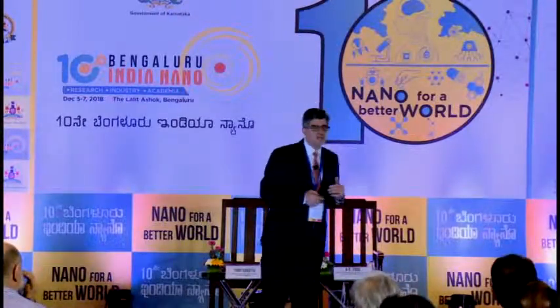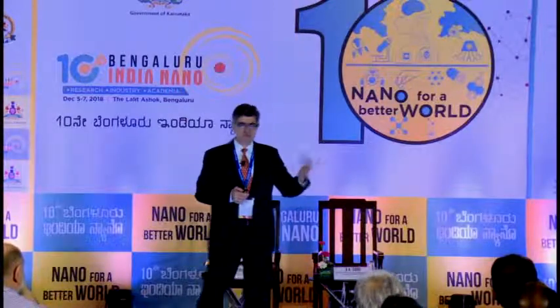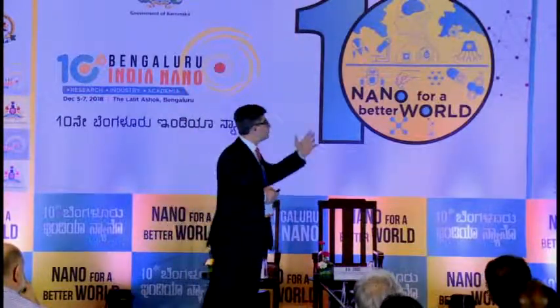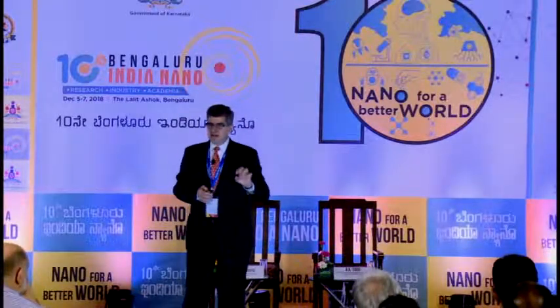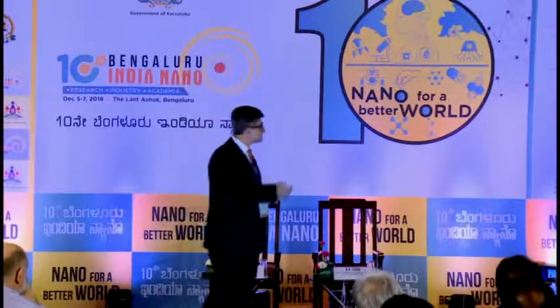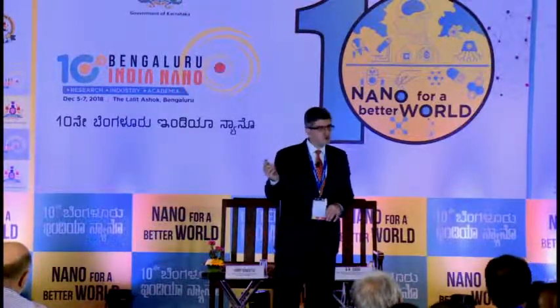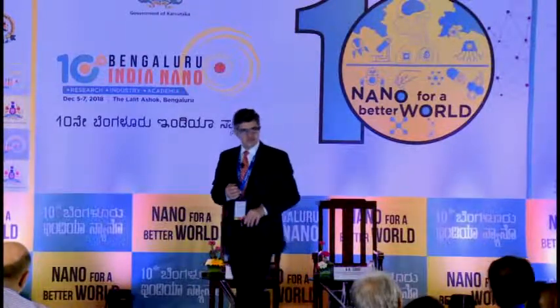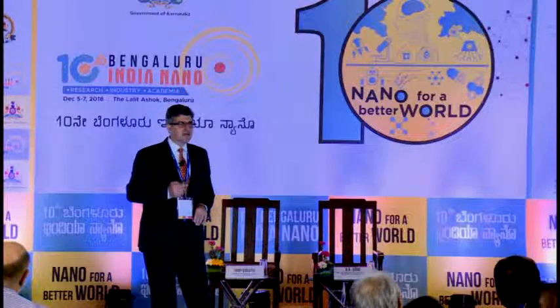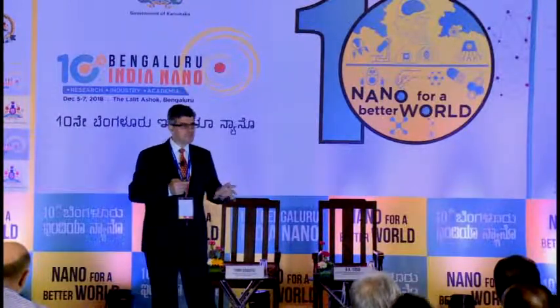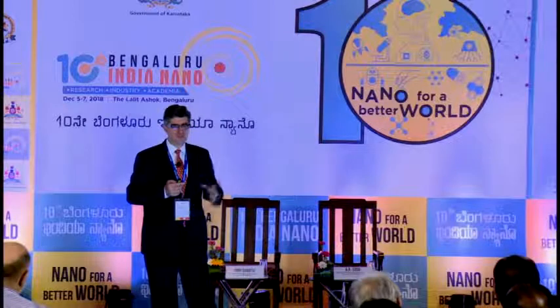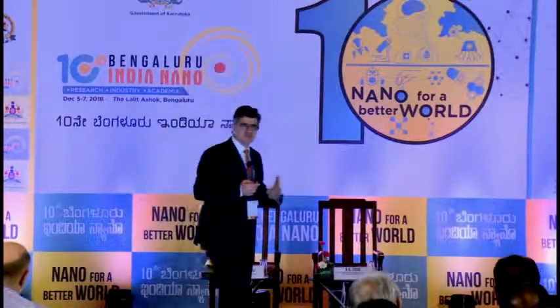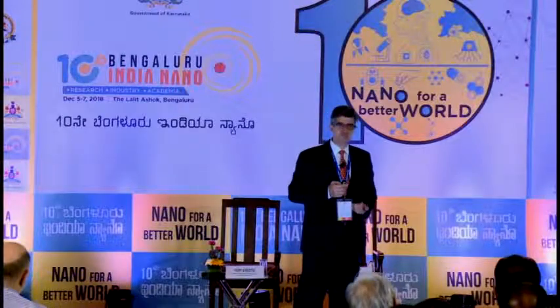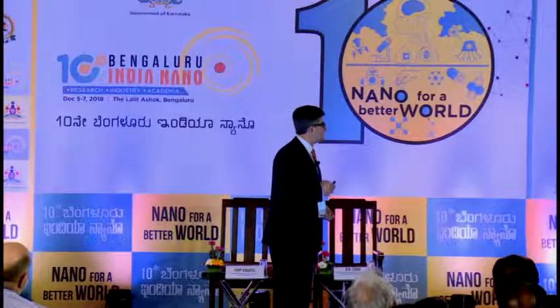One of the applications that is being widely explored now, there are already a couple of review papers on this, is using it for thermal therapy. We can shine light in the near infrared, like 780 nanometer, for example, for Ti3C2, or infrared for some MXenes like Ti4C3 and others, and destroy tumors by heating the sample with benign irradiation, heating deep in the body, much deeper than, for example, gold nanoparticles, which give plasmon resonance in the visible range and can be used only for skin-deep tumor destruction.